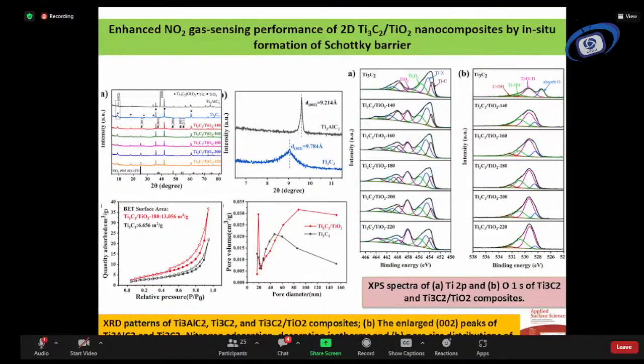So this is the first one we published recently, maybe last year, in Applied Surface Science: enhanced NO2 gas sensing performance of two-dimensional MXene, this Ti3C2 and titanium oxide composite, by in situ formation of a Schottky barrier. These are typical figures, for example XRD, XPS, and others, including convoluted XPS figures. If some of you have a material background, you can easily see these XRD peaks are well aligned with what we have prepared.